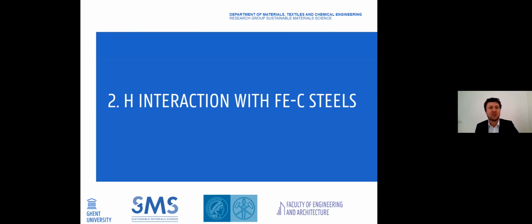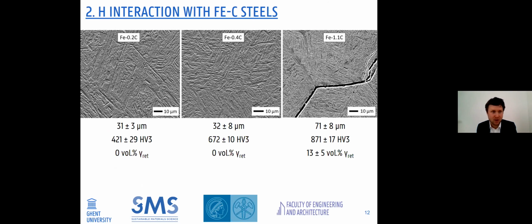Let's now focus on the interaction with these iron carbon steels and the hydrogen interaction with them, so without the addition of aluminium. What do we have? Well, we have 0.2, 0.4 and 1.1% of carbon. These materials were produced by vacuum induction melting under an argon atmosphere and then cast and hot rolled until 1.1 millimeter. After that, we austenitized the materials around 100 degrees C above their AC3 temperature for 20 minutes, followed by a brine quench to obtain a martensitic microstructure.